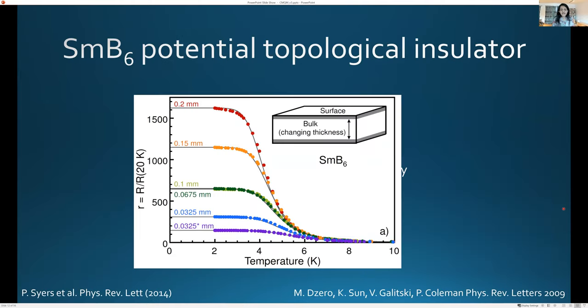This is initial work by Dzero, Sun, Galitski and Coleman, postulating that samarium hexaboride is a topological insulator. And here is some of the preliminary work that provided possible evidence for this as a topological insulator, given the fact that when the material is thinned, the surface conductivity stays the same, but the bulk resistivity changes. And as a result of that, the ratio of the resistivity at low temperatures, which is the surface resistivity, to that of the bulk changes as the thickness of the sample is changed. And that was one of the signatures one would expect for a topological insulator.